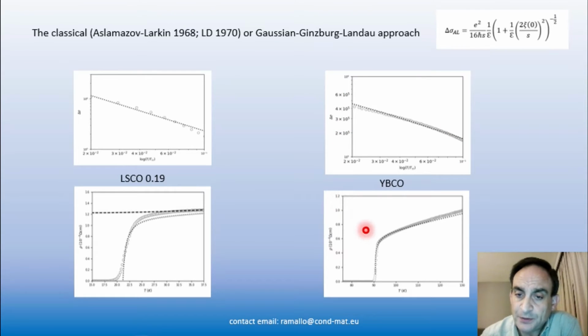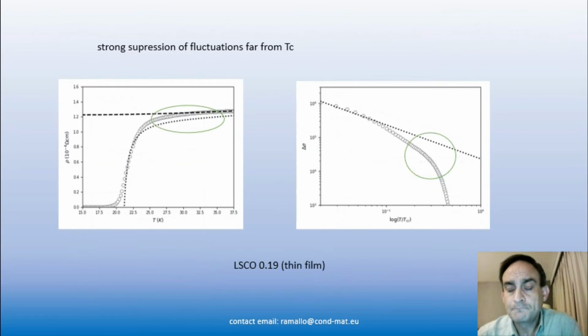This is for YBCO, optimally doped, this is for LSCO, overdoped. But if we represent the same as just plotting the resistivity versus temperature, we see that this approach really works very well in the transition, but there are obvious problems if we go up in the transition or in the tail. So the agreement is certainly not complete. So let's talk first about the high temperature region.